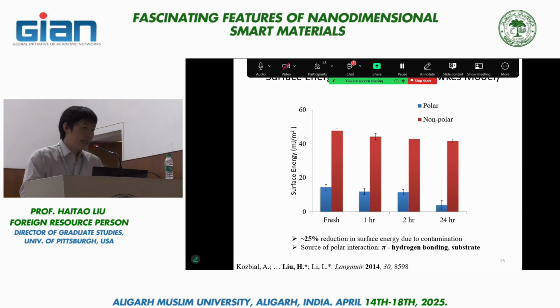I just told you graphene is non-polar, and it's indeed non-polar because there's nothing other than carbon atoms. Our hypothesis right now is that there's a very strong hydrogen bonding interaction, and this would originate from the proton in water being partially positively charged, interacting with the pi system of graphene, which is negatively charged.